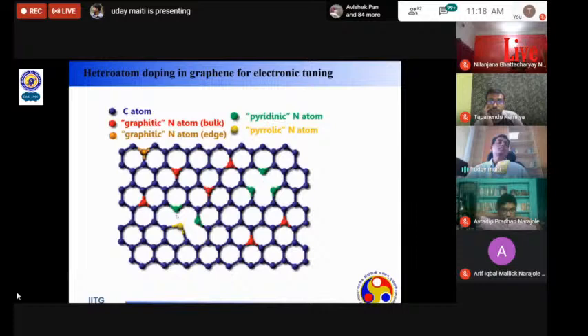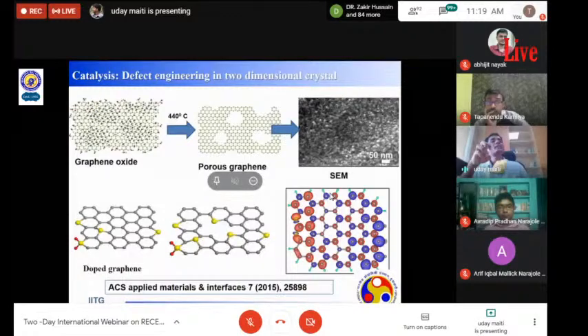But you can see that at the edges where there are some defects, if we have some pores or defects, even if this atom has a larger size, there is no issue. So we took this as a theory: if we can create some pores, we can incorporate some big heteroatoms. But how to create the pores within graphene? So we started with graphene oxide, which, as I mentioned, is a functionalized form of graphene. But there were already reports that in graphene oxide there are some patches, a region where there is no functionalization. This is graphene-like, and there is also some patch here. This is functionalized. So this is a percolated network of graphene and functionalized graphene.